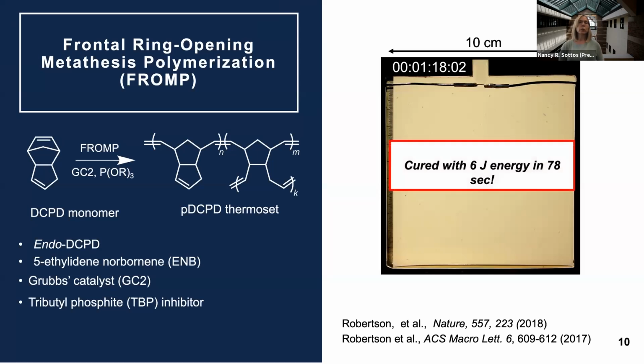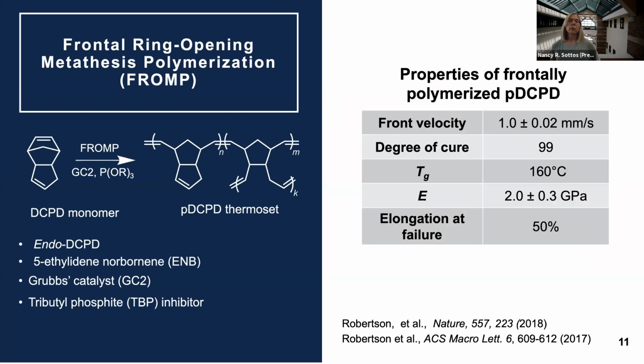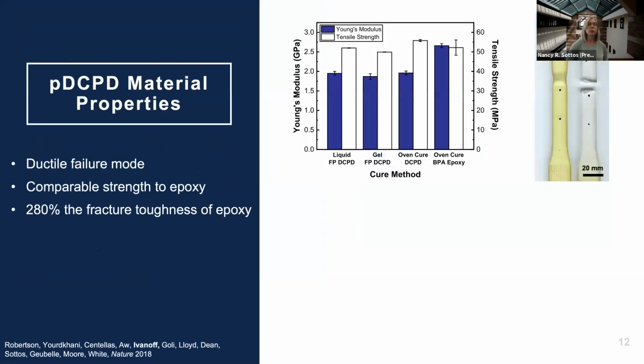And this thing is cured with just 6 joules of energy in 78 seconds on a desktop. The front velocity is about a millimeter per second that you see there. The degree of cure is quite high. But what's most remarkable to me is that the glass transition temperature of this material is 160 degrees C. It's got a Young's modulus of about 2 GPa and a good elongation at failure, about 50%. So it's got great engineering properties comparable to those of an aerospace grade thermoset.